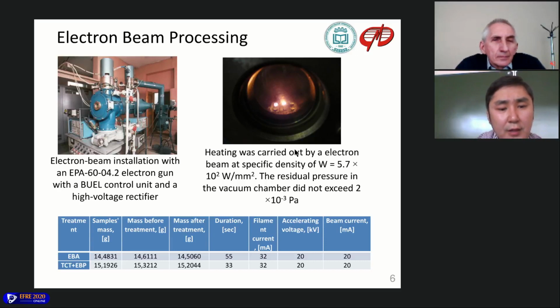For example, initial mass with treatment paste was 14.6111. After EBA process, the mass reduced to 14.5060. So the sample lost approximately 0.1 gram. And duration of the process was 55 seconds, and for the second process, approximately half of a minute. Next.